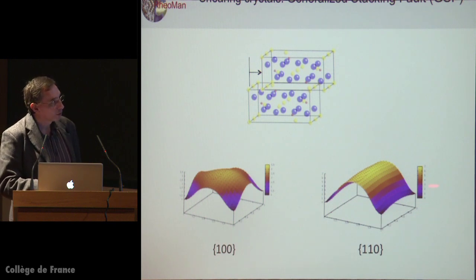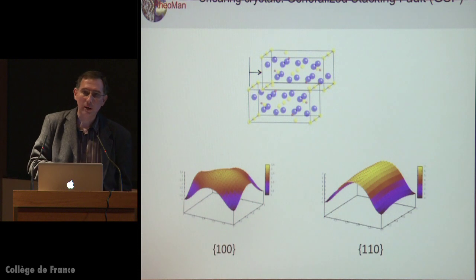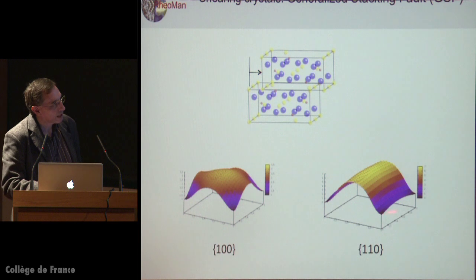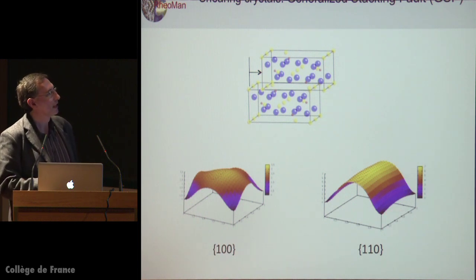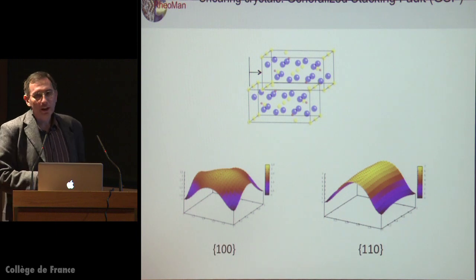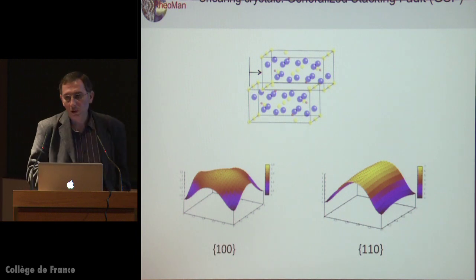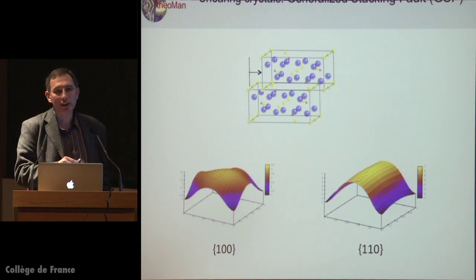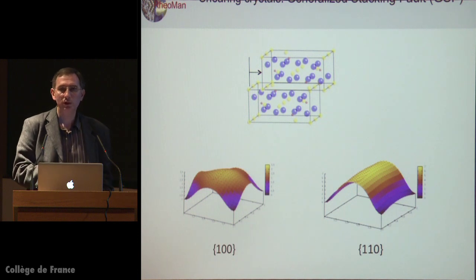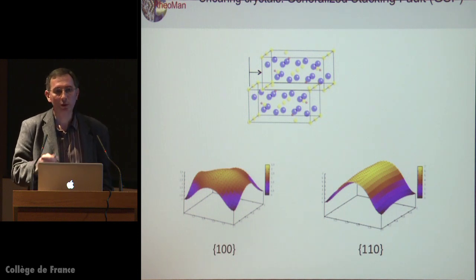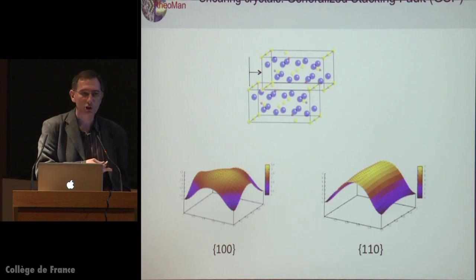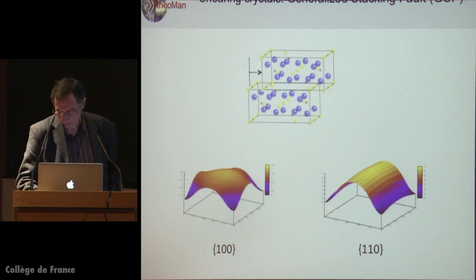And you can find what we assume from the ceramic people. We can find again that the easy slip or shear path here is half 110, for instance, or here you have the other shear path. What's the advantage of doing that? It's not to find again what we knew. Because we can do that on a limited number of atoms, we can do that by first principles, so we can properly take into account the influence of pressure and of the change of the electronic structure as a function of pressure. So this is a way to do that properly.